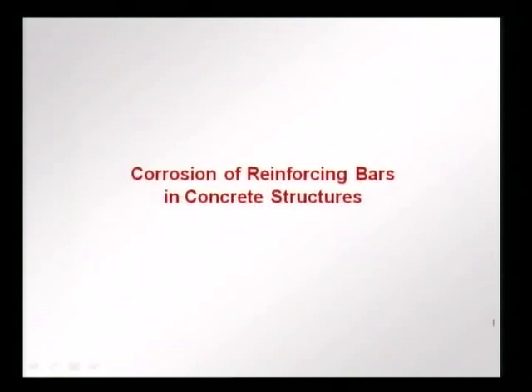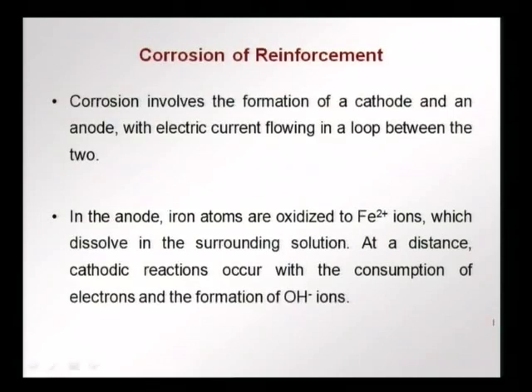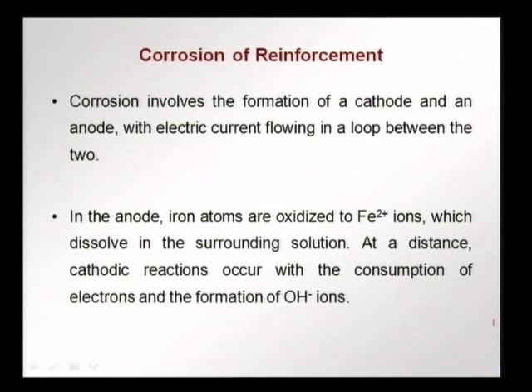Now let us look at corrosion of the reinforcing steel bars within concrete. Most concrete structures have reinforcement that could be prone to corrosion. Corrosion is an electrochemical process — it is more stable for a material to oxidize and return to its natural state. Since steel is embedded in concrete, the concrete also participates in the corrosion process. At the anode, iron is oxidized into Fe²⁺ ions which dissolve in the surrounding solution; at a distance, cathodic reactions consume the released electrons and form OH⁻ ions.